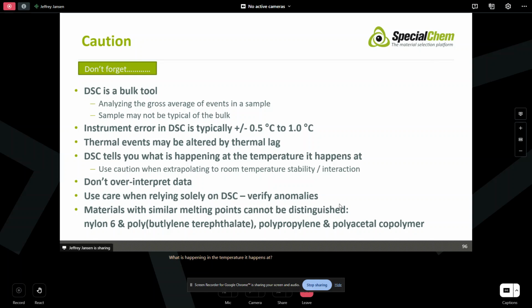So use caution when extrapolating back to room temperature for stability or interactions or reaction kinetics or things like that. Don't overinterpret the data. Again, sometimes there's noise in the sample. You may not get to understand every small blip that is present in the thermogram. Verify any anomalies you see. Like I said, if you suspect that the material has been degraded, then DSC gives you that warning signal, but may not be the best indication of that.